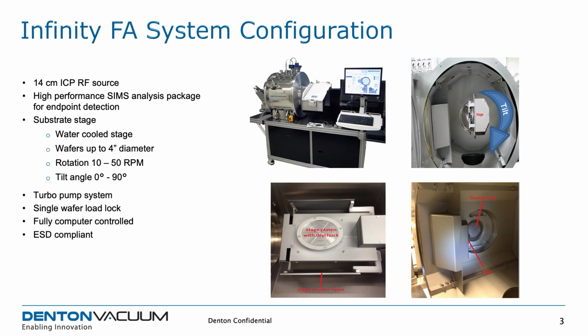So on top of that, we have added the secondary ion mass spectrometer so that as you etch through the layers, you can observe like when the copper traces go up and down and stop exactly where you need to, whether that's in a metal layer or a via layer or other. So the substrate stage is water cooled to keep the chip cool during etching.